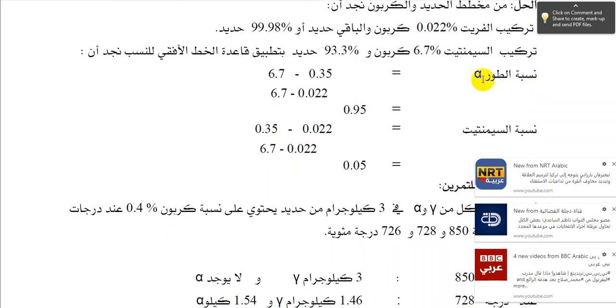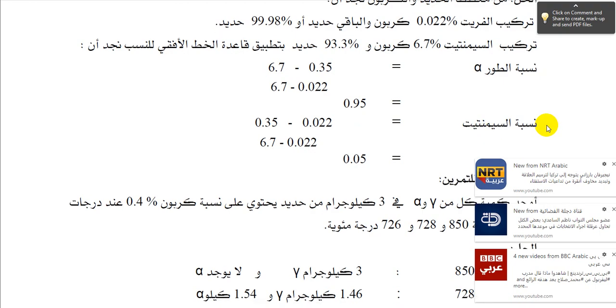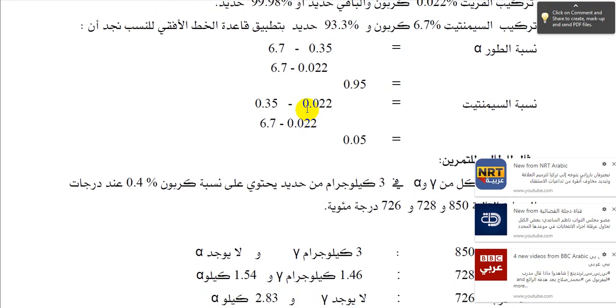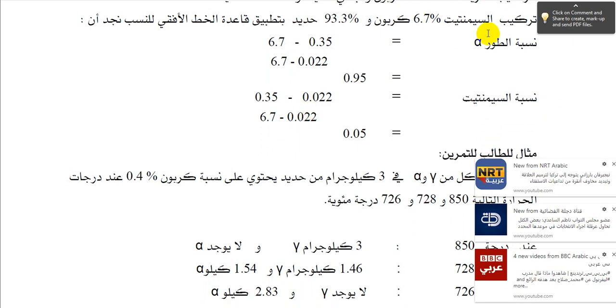The alpha phase proportion equals 0.95. The cementite proportion is 0.05. Cementite, as you can see right here, has a composition of 6.7% carbon and 93.3% iron. By applying the lever arm technique for proportion computation, the cementite proportion is (0.35 minus 0.022) over (6.7 minus 0.022), which is about 0.05.